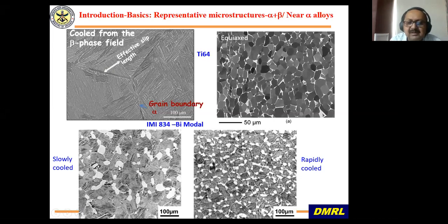For applications in aero engines, what you have is these bright regions are primary alpha. This happens when you deform the alloy. I will talk about it slightly more in detail, but this structure as such is called bimodal structure. Why is it called a bimodal structure? Because there are two types of grain. One is primary alpha, which you can see, and another is transformed beta. Okay, this is a transformed beta. It has alternate layers of alpha and beta, as in this structure, which is called a transformed beta microstructure.